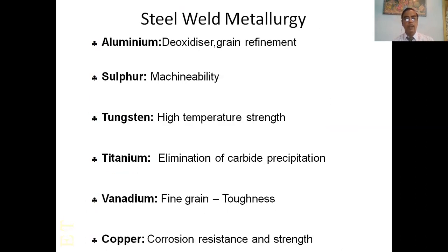Steel weld metallurgy: aluminum as deoxidizer and for grain refinement, sulfur for machinability, tungsten for high temperature strength, titanium for elimination of carbide precipitation, vanadium for fine grain toughness, copper for corrosion resistance and strength.